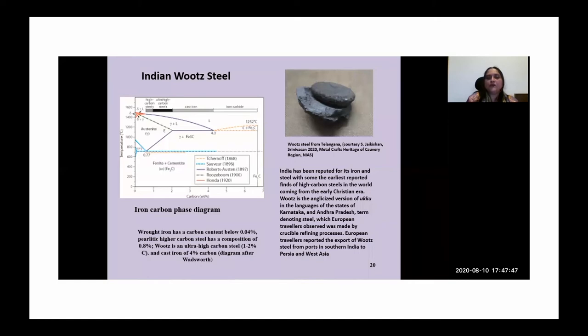And wootz is interestingly a particular kind of alloy, which is an ultra high carbon steel, which forms in a composition range of about 1 to 2% carbon. And so that's the topic that I'm going to now talk about a bit more. And cast iron has about 4% carbon. Now, cast iron, of course, is a brittle material, and it's not actually very workable. And it's also a difficult technology for smelting. You need to have a blast furnace and so on.